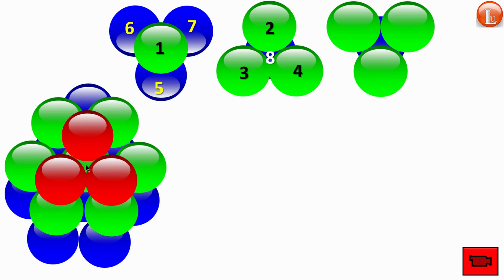and therefore the fact that it is contributing to 8, so each void will have only 1/4 contribution, because each void is made up of 4 atoms. So each void has only 1/4 for an atom, and an atom is associated with 8 of them. So 8 into 1/4 makes it 2. So per atom there are 2 tetrahedral voids, and therefore if the rank of a unit cell is x, then the number of tetrahedral voids will be 2x, twice the number of rank.